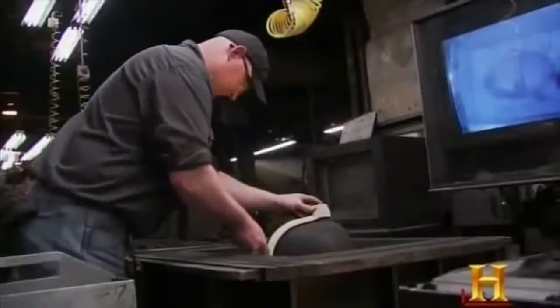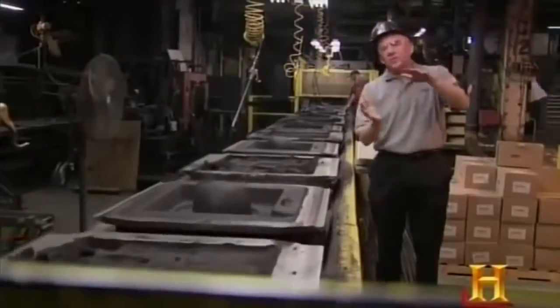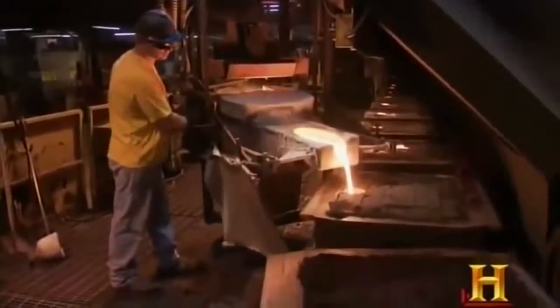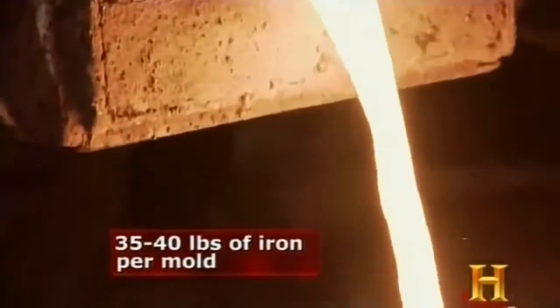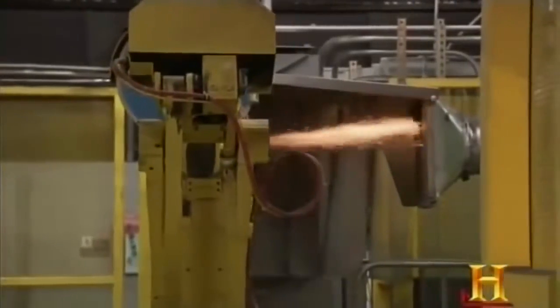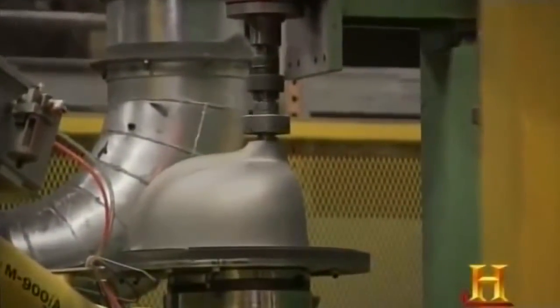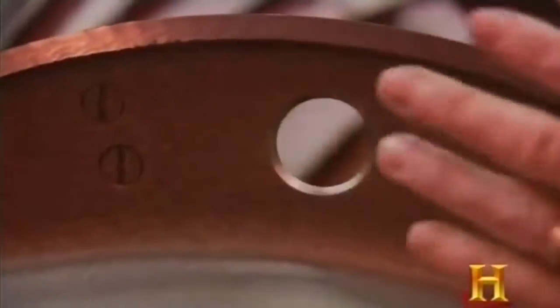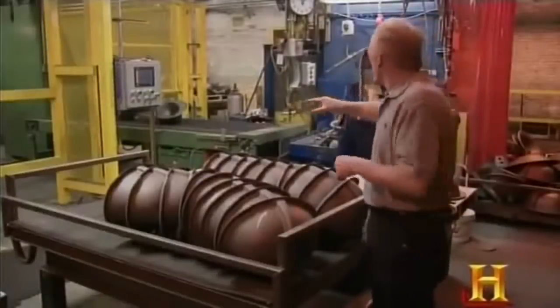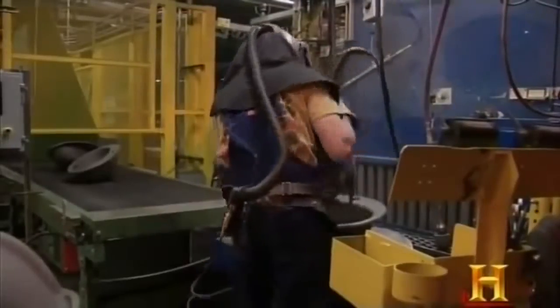During the molding process, you have two halves of a mold. When put together, there's about a quarter of an inch in between, and that's what fills with the iron. The melt is brought over by forklift and poured into the molds. It takes just a minute for the molten metal to solidify, and another couple of hours for the sinks to cool enough to be sent for grinding and cleaning. That's done robotically, clearing out the drain hole and supply hole, before the piece moves on the conveyor to the grinder.